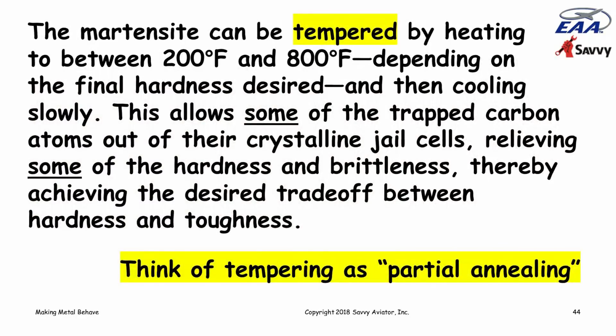But it can be tempered by heating the metal back up to a lower temperature, somewhere between 200 degrees and 800 degrees, depending on what the final hardness desired is, and then cooling it slowly. This allows some of the trapped carbon atoms out, but not all of them. So it relieves some of that hardness and brittleness, but not all of it. And by doing this hardening and then tempering, we can get the hardness versus toughness of the metal to the exact trade-off where we want it.